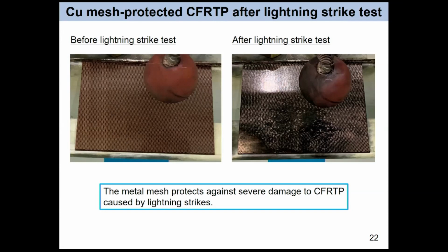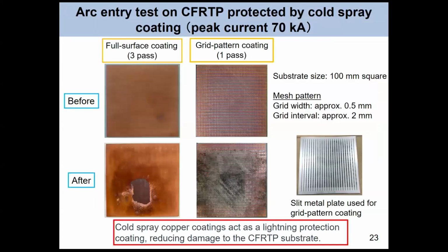So we performed the same experiment on copper coated CFRTP. This test was 40 kiloampere, but we used 70 kiloampere for the cold spray samples. The upper figures are before the lightning test, and the lower figures are after. We tried the full surface coating, and also a grid pattern coating, similar to a mesh pattern, so metal mesh.